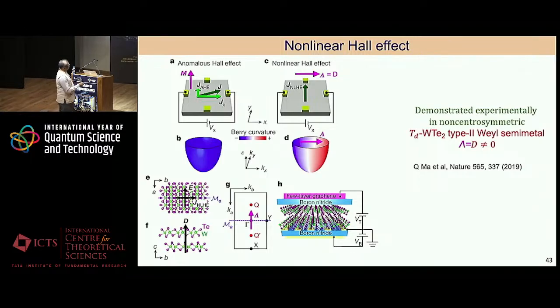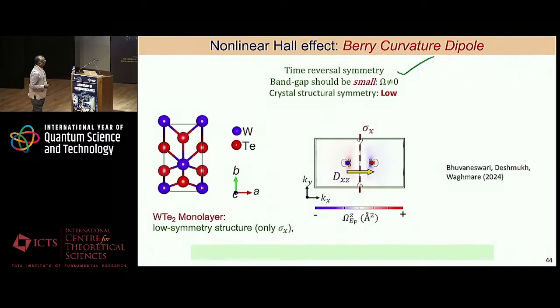Now, the experimental verification of the nonlinear Hall effect came in 2019 from Pablo Jarillo-Herrero's group. Basically, the anomalous Hall effect gives rise to a transverse electric current at the same frequency, so the overall current has an angle with respect to the incident field, whereas in the nonlinear Hall effect, the effect is very clean, although it is weak because it's a nonlinear effect. For a field along the x direction, the Hall current at double the frequency or zero frequency, which is rectification, is always perpendicular to the applied field. Which is a very nice thing in terms of measurement convenience in experiments.